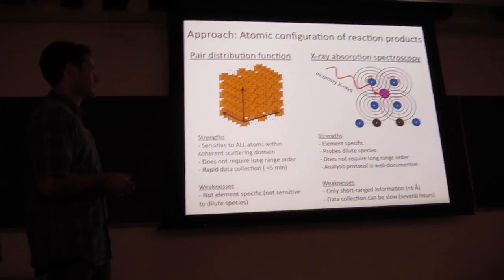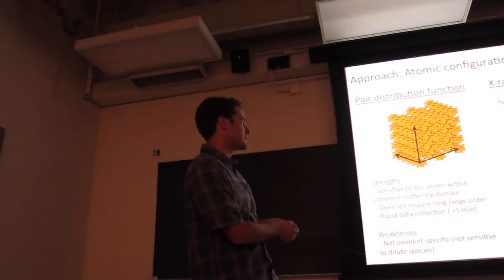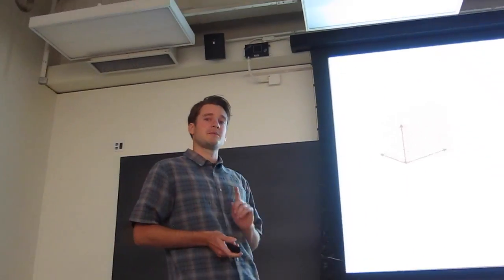Well, we can see what the data looks like. But the PDF is not element specific. It sees every single atom within the solid. So if you're looking for something that's dilute, say arsenic at the lowest concentration in our samples, you would use X-ray absorption spectroscopy because it is element specific.